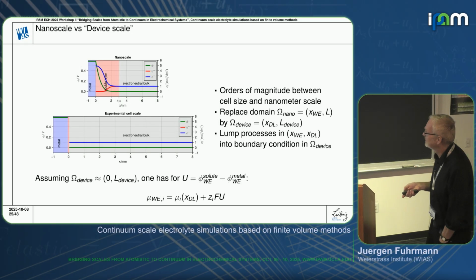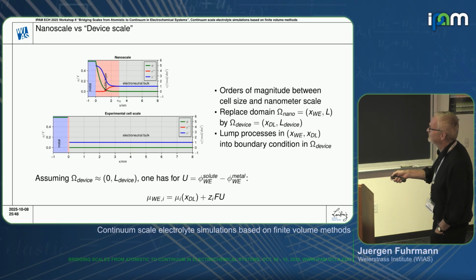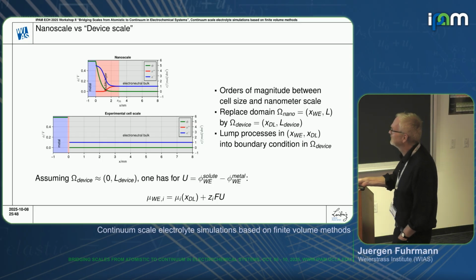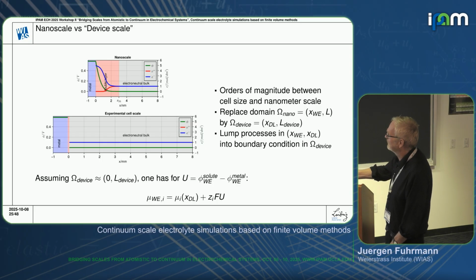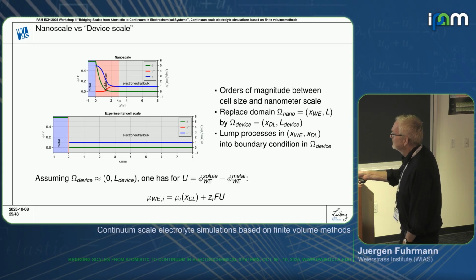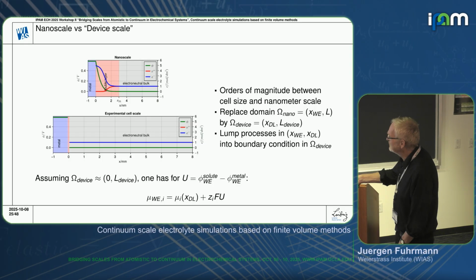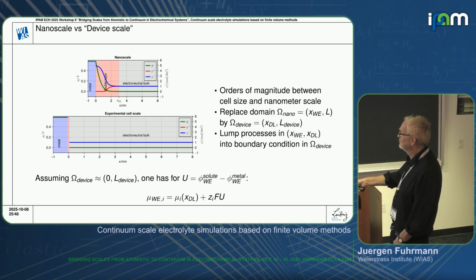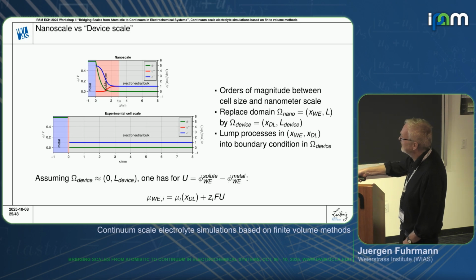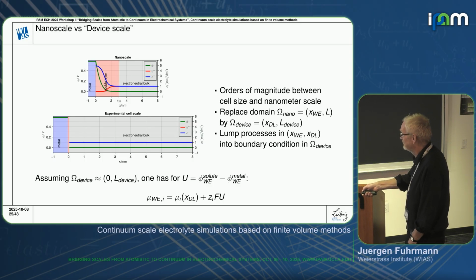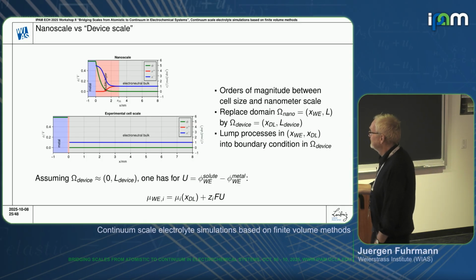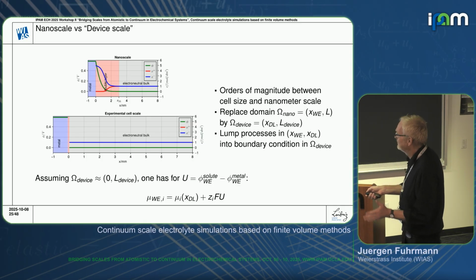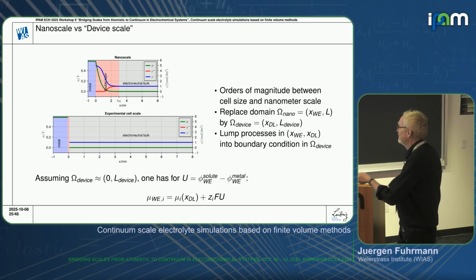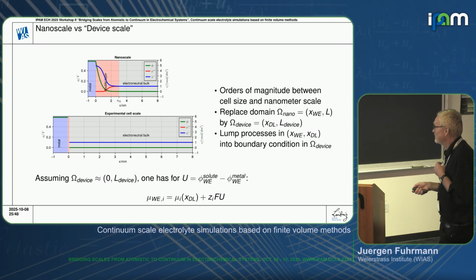So then we have kind of two ways to look at this system. We have the nanoscale, where we have our boundary layer resolved. And we have, let's say, what I call the experimental cell scale, where we assume that we have the electroneutral bulk, where everything in the double layer collapses into a boundary condition, and we get a new interface condition and a jump of the electrostatic potential by the size of the applied potential. And this gives us a term which can be reformulated into something resembling a Butler-Volmer equation.